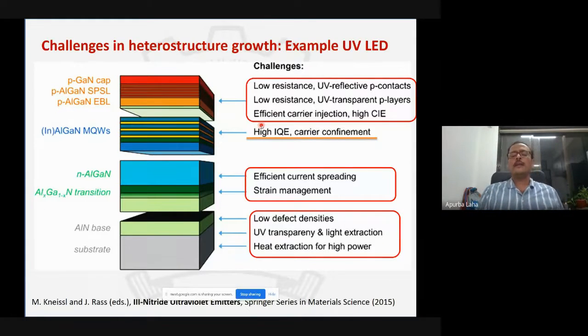So if you look at each of the layers, each of these components that you see here has its own challenge. First of all, if you want to have very high current injection, unlike silicon, for example, we don't talk about the contact. Here, getting a good ohmic contact is a big challenge. So many researchers across the world are trying to optimize and improve the contact, to have better injection of the current for an aluminum gallium nitride based layer, for example.